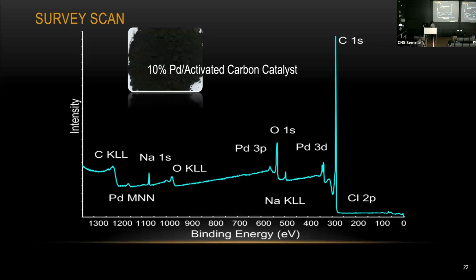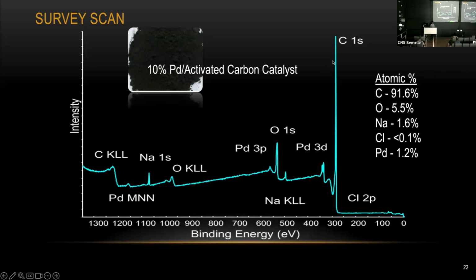And then you take all this peak intensity, then we can get some kind of quantification. So based on the data you're seeing on the screen here, the machine calculator shows almost 92% carbon, and the palladium is only 1.2%. But when we prepare a sample, this percentage should be 10%. So that's what's going on here.